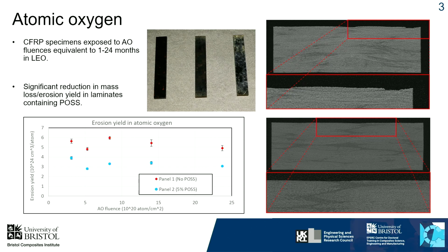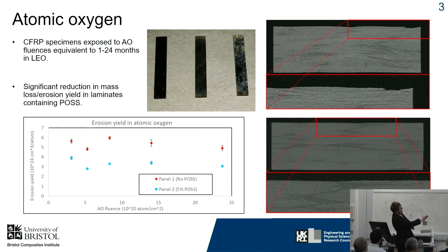And if you can see, I don't have a laser pointer, but in the post-exposure CT scans of the materials, you can see that the polymer component in the top image has been eroded very preferentially over the fibre component, the fibres being the lighter part. And then in the second image, you can see there's a large resin pocket in the middle, which hasn't been eroded to anywhere near the same degree. And that's the panel containing POSS. So you can see the very beneficial effect of the addition of POSS.